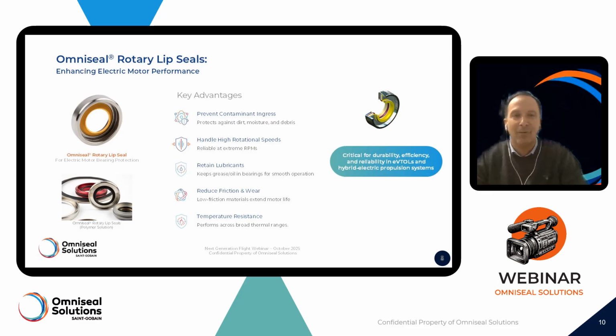Typical speeds our rotary lip seals can withstand are up to 35 meters per second. And also with special designs, we can even go up to 100 meters per second, also depending on other application conditions, of course. Also, pressures up to 35 bar are no problem for our rotary solutions. The wide temperature range can also be seen as a key benefit, ranging from minus 50 degrees C up to 230 degrees C. And that is helping us to achieve high sealing performance in this application.